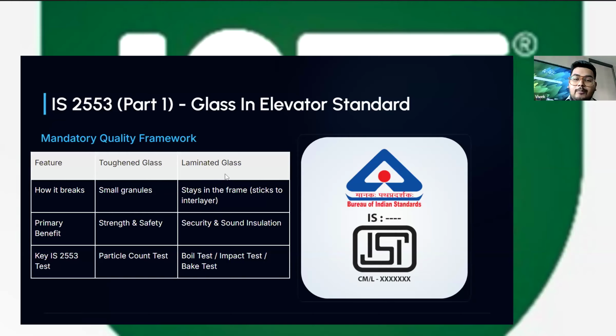Secondly, if we talk about laminated glass, it majorly has three tests: the boil test, impact test, and bake test. If I talk about the boil and bake tests, there is only one difference, that is water and air. In a boil test, we make a laminated glass and put it into 100 degree boiling water for around 2 hours to see how the glass with the interlayer reacts with the boiling water.